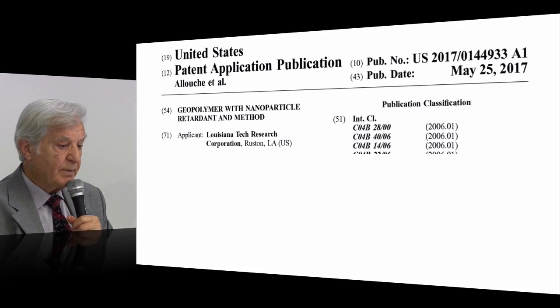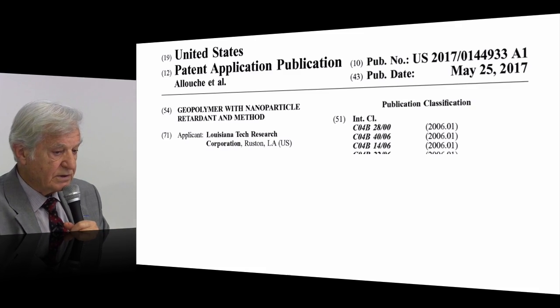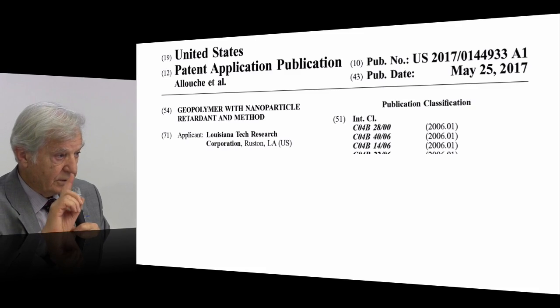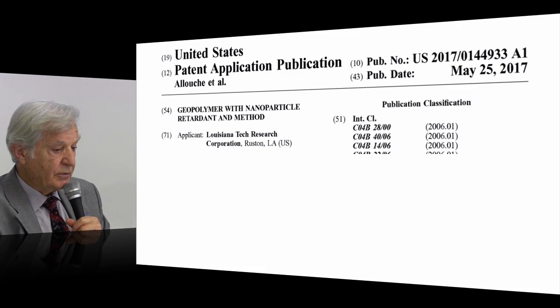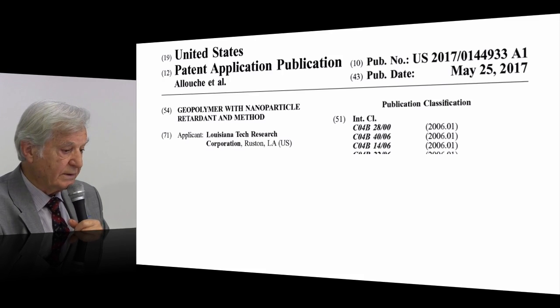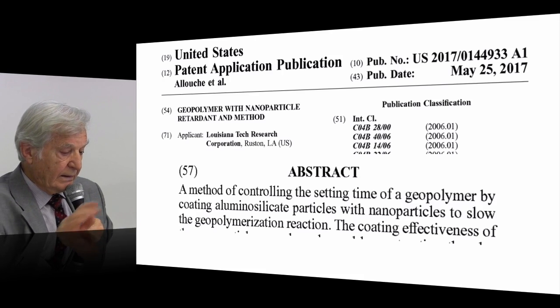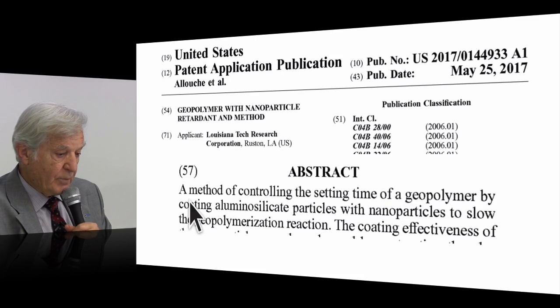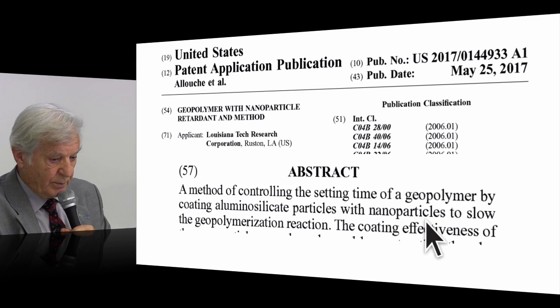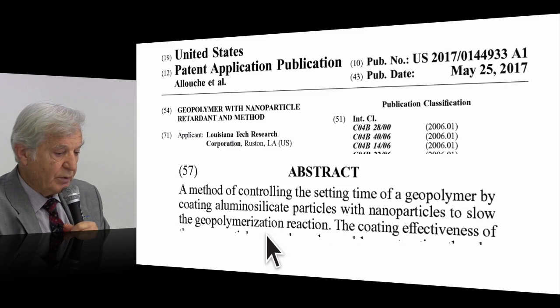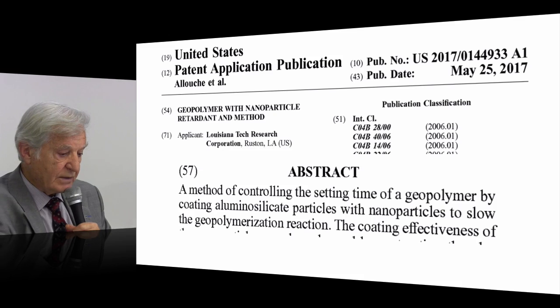There is an interesting patent that has been published this year, published, not granted, in the US by a friend from Louisiana Tech University. The abstract: a method of controlling the setting time of a geopolymer by coating aluminosilicate particles with nanoparticles to slow the geopolymerization reaction, the coating effect, and so forth.